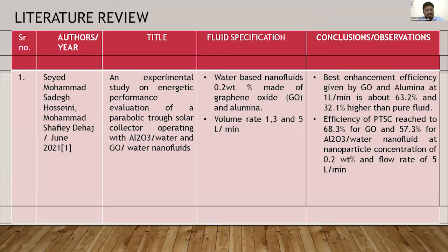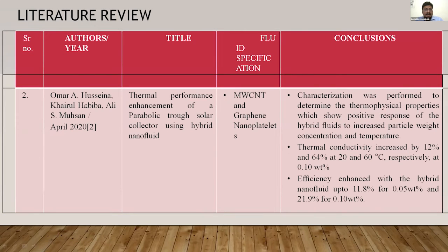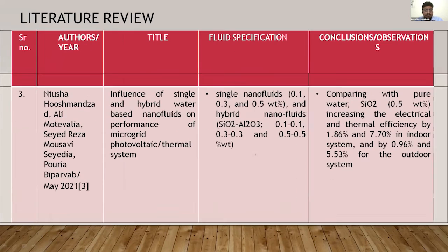These are the literature reviews which I have done. Syed Mohammed et al. experimented with nanofluids of graphene oxide at three flow rates, 1, 3, and 5 liters per minute, and got higher efficiency. The base fluid gave a different efficiency, and the efficiency with nanofluids was higher by 63%. Omar used multi-wall carbon nanotubes, which increased the thermal conductivity by 12% to 64% at different temperatures. Another person used single nanofluids